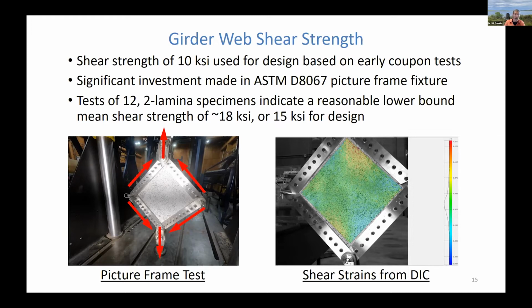I say lower bound because we got edge failures on these specimens. We didn't actually get a material shear failure, but we got failure in bearing of the fasteners on the edge of the specimen before we actually reached its shear strength. If we applied our statistical strength reduction factor of 0.85, that would take us down to an ultimate shear strength for design of about 15 KSI.